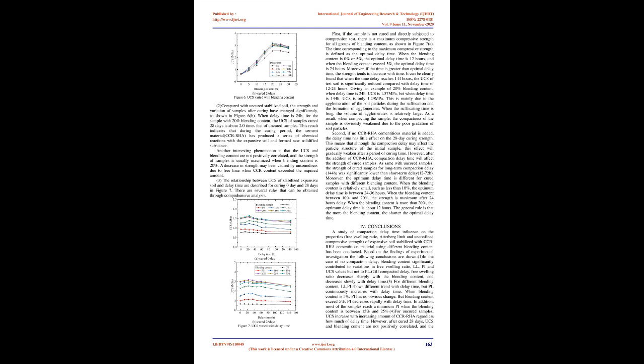2. Compared with uncured stabilized soil, the strength and variation of samples after curing have changed significantly, as shown in figure 6B. When delay time is 24H, for the sample with 20% blending content, the UCS of samples cured 28 days is about 2.0 times that of uncured samples. This result indicates that during the curing period, the cement material, CCR-RHA, has produced a series of chemical reactions with the expansive soil and formed new solidified substance.